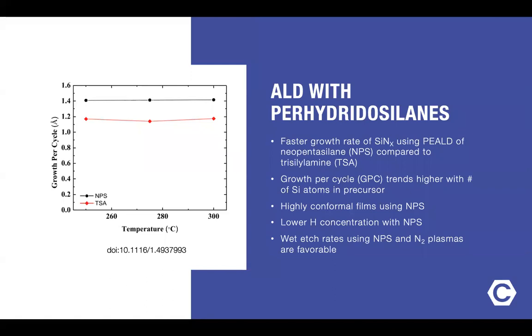So looking at perhydrosilanes that have been evaluated with ALD, there are only a few examples. Here is one using neopentasilane and comparing that to trisilylamine to give rise to a silicon nitride film. So we see that even though the neopentasilane is reacted with the nitrogen plasma, so more of a bimolecular reaction, it still has at least a 10% higher growth rate than trisilylamine.